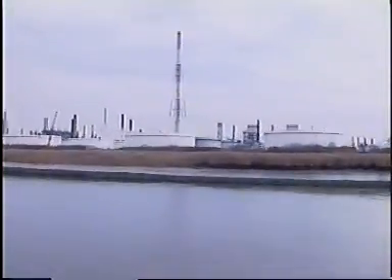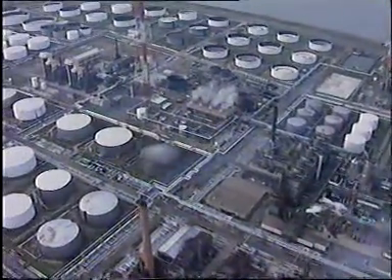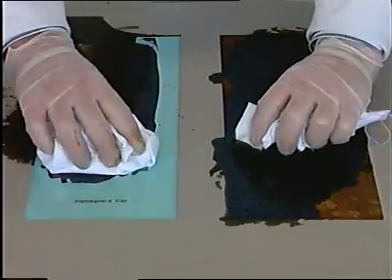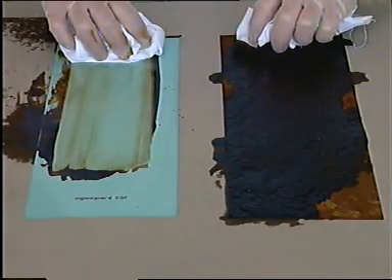So, the result after nearly 5 years in service? Perfect. Pits remained sealed, and the coating was in exactly the same condition as when the tank was refilled after application and curing. This application clearly demonstrated that where corrosion from underneath the tank was not a problem, which was the case at this Fina site, the system performed very well without the need for glass reinforcement. The ease of cleaning of SigmaGuard CSF enabled tank cleaning time before inspection to be reduced from 3 weeks to 2 days.